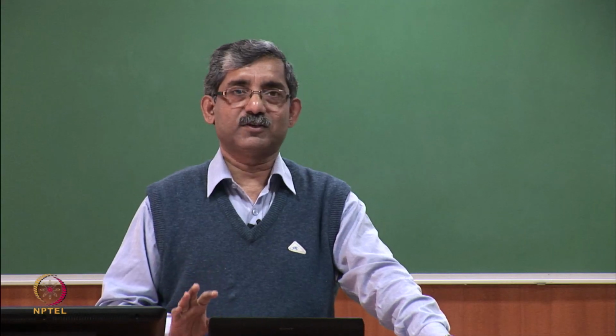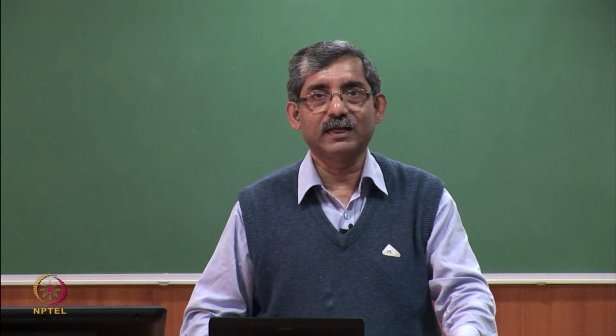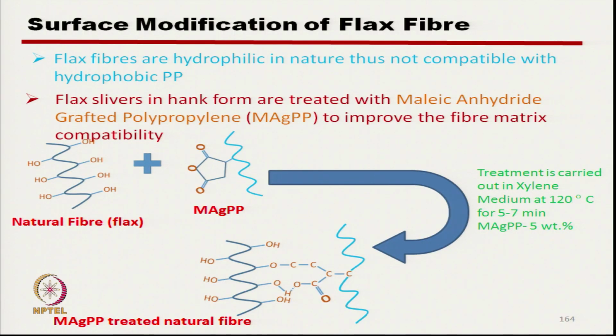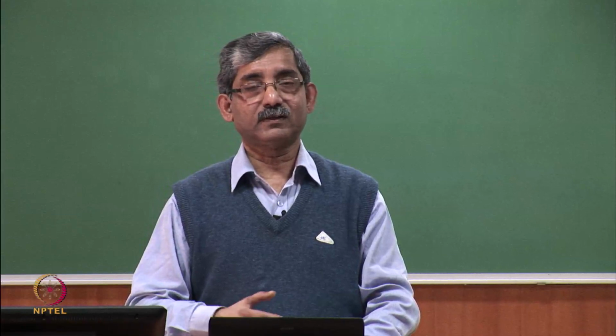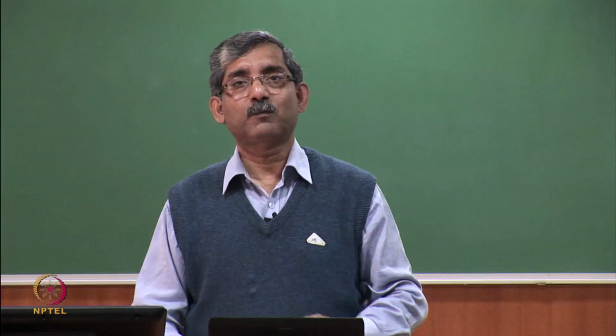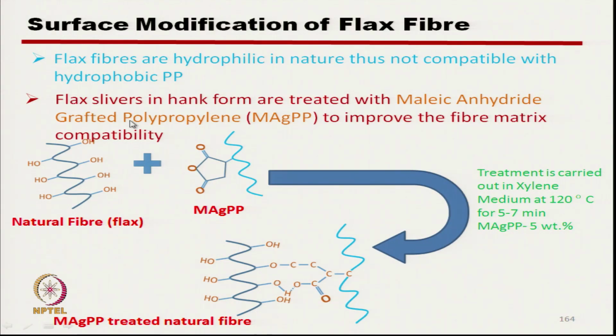As already mentioned, flax being hydrophilic in nature is not compatible with the hydrophobic polypropylene, which is used as matrix. So, surface modification of flax was done using maleic anhydride grafted polypropylene, which is known as MAGPP. Using this MAGPP treatment, we can use the surface modified flax fiber as the reinforcing material when polypropylene is used as matrix. This is the surface treatment.